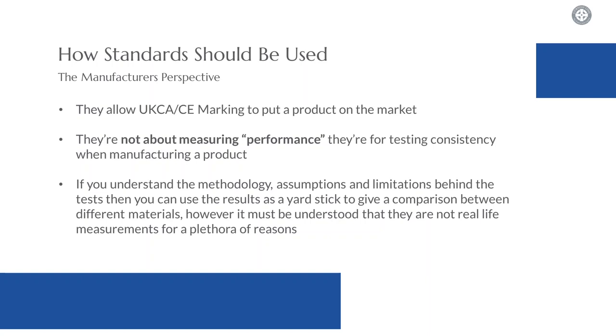This becomes a problem when these standards are being used for specification, because it is being taken for granted that these are measurements of performance of a mortar. To be completely fair, if you do understand the methodology, the assumptions, and the limitations behind the tests, then you can take these results and use them as a yardstick to give a comparison between the different materials. So to use the water absorption example: you can have a material which saturates in 20 minutes and a material which saturates in 80 minutes, and in real life you can say in all likelihood the one saturating in 20 minutes will still be more porous — but you must understand that those figures are not what you're going to achieve in real life.